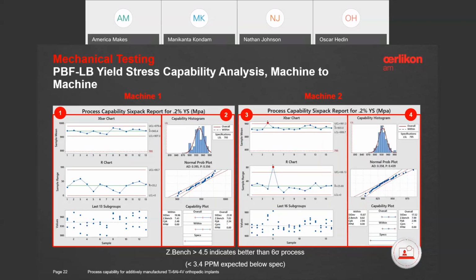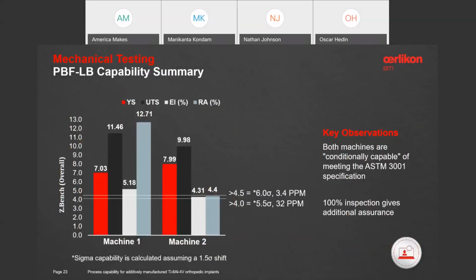So in summary, dashboarded all the z-scores for all the mechanical properties for each machine 1 and machine 2. One thing to observe is both machines are very similar to each other in the yield strength and the ultimate tensile strength and percentage elongation. However, we see some variation in percentage reduction, but that does not stop us from concluding that these machines are highly capable to meet the specification limits provided by the ASTM standard. Also, for additional assurance, we do 100% mechanical inspection to make sure we are always producing good parts.